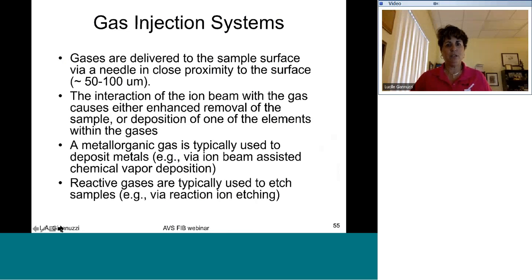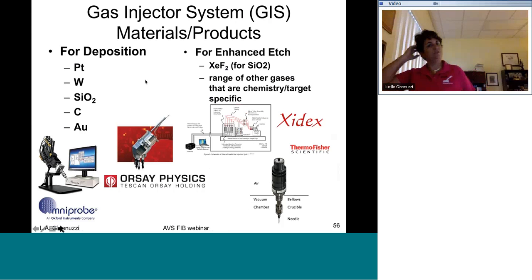Okay, so there's our prototyping. Gas injection systems: typically we're using a metalorganic gas for deposition, and we're using reactive gases to etch. Gases are delivered to the sample surface with a needle, generally in close proximity to the surface. How the gas interacts with the sample will determine whether you've got deposition or enhanced FIB etching. There are a lot of different gas injectors out there for deposition. You can do platinum, tungsten, SiO2, carbon, gold, and enhanced etch with xenon difluoride and a range of other gases. There are a lot of vendor-only products or third-party vendor products out there for gas delivery.